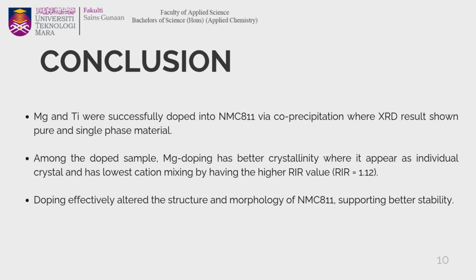And for the conclusion, in this study, it is proven that magnesium and titanium were successfully doped into NMC 811 via co-precipitation, where XRD results showed pure and single-phase material. The second one is that among the doped samples, magnesium doping has better crystallinity, where it appears as individual crystals and has the lowest cation mixing by having the higher RIR value. And the last one is that doping effectively altered the structure and morphology of NMC 811, supporting better stability.